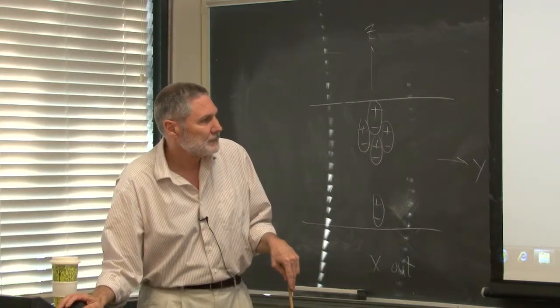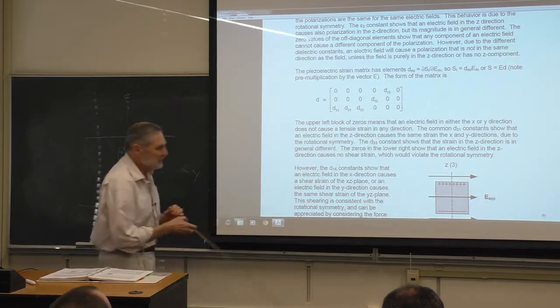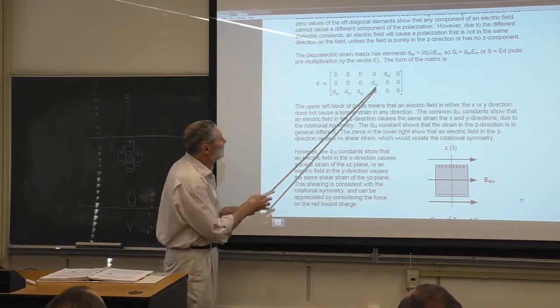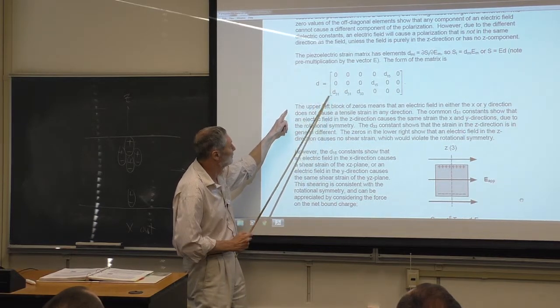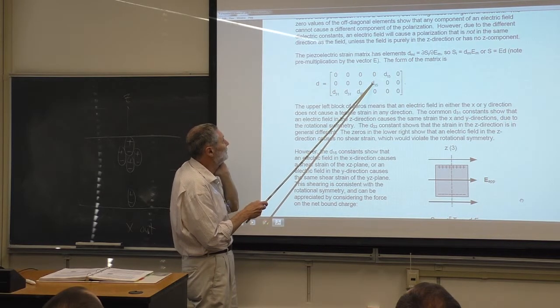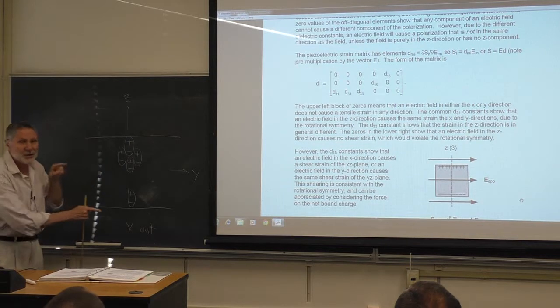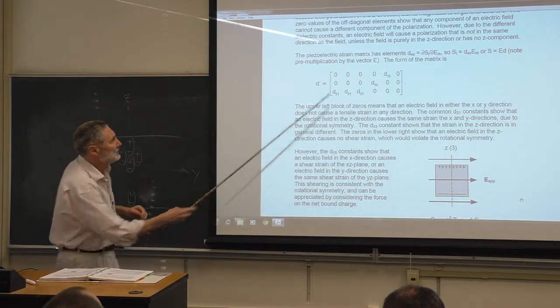The D₁₅ elements describe what we just explained: if you have an electric field in the y direction, when you do the vector-matrix multiplication you pick up a shear associated with the x component — a shear of the yz plane. It's reasonable because the bound charges are forced in opposite directions. That's why those elements are there. Now let's look at the consequences for piezoelectric behavior — the symmetry really forces just about everything: the zero elements and non-zero elements.